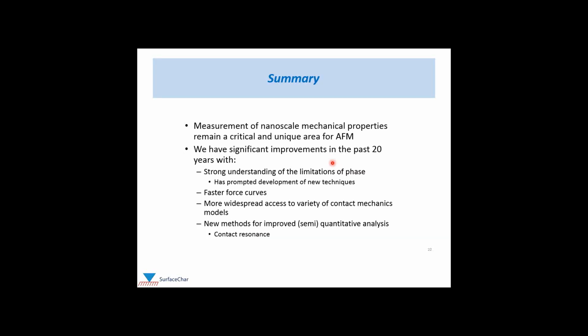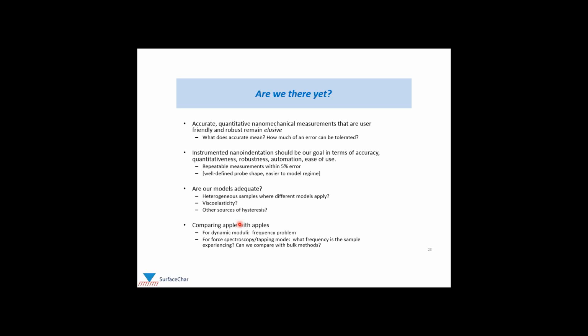So in summary, nanoscale mechanical property measurements really are a critical and unique area for AFM. That's not going to change. As I said in the beginning, AFM is intuitively designed to make these kinds of measurements. We have made significant improvements in the past 20 years, with strong understanding of limitations of phase, improvement in force curves and the models we use, and newer methods like contact resonance. But trying to address the issue that I posed at the beginning, what is really the status of quantitative nanomechanical measurements? Are we there yet?